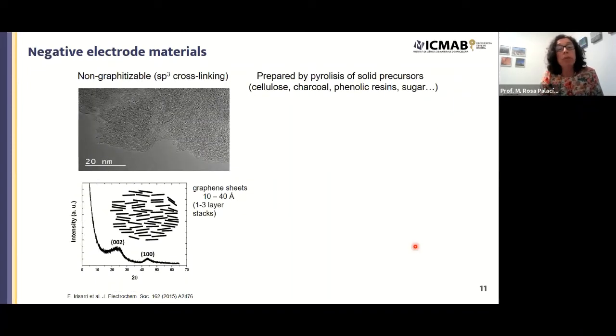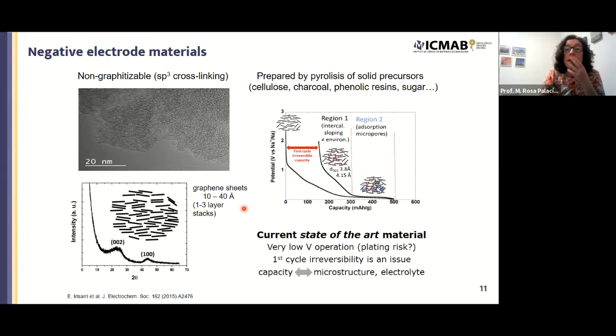On the negative side, as I was mentioning, only hard carbon can be used. This is prepared by pyrolysis of solid precursors, and typically you get these diffraction patterns. This is a very disordered material consisting of graphene sheets between 10 and 40 angstroms in size, stacked between 2 and 3 layers. And this is the voltage versus capacity profile.